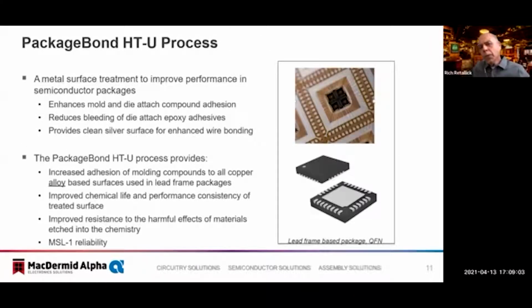Next. If we consider our PackageBond HTU process, this is a metal surface treatment enhancing the bond between the epoxy mold polymer and the metal substrate or the lead frame. This, again, improves a stronger bond between these substrates. It also is designed to eliminate or reduce the bleed associated with die-attach adhesives, and it leaves a clean surface for improved or enhanced wire bonding. Next.